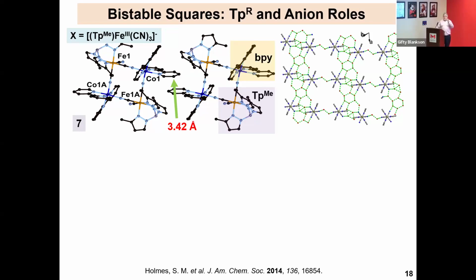And during the course of the reaction, we could do lots of things. By taking this TpMe, or tris(3-methylpyrazolyl)borate, it's less donating than the other ligands. The idea is if we shift the redox potential for the iron in a more positive direction, then we should shift the transition temperature where electron transfer happens to a higher temperature as well. Right? And so that was our working hypothesis. We kept the ligands the same on the cobalt because we wanted to just change one variable.